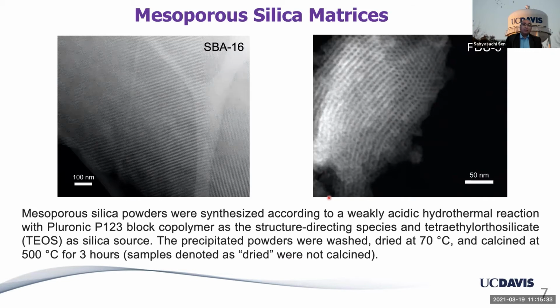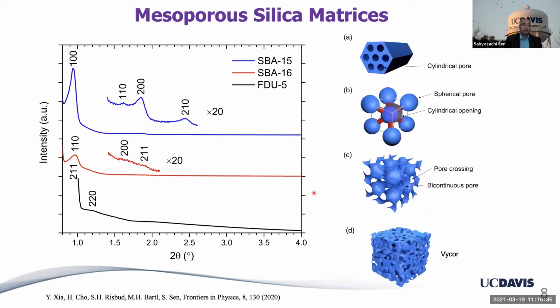So these are a couple of examples of such materials that we have used. Here are some X-ray diffraction patterns from these mesoporous lattices. They agree very well with the literature values. So these are not novel materials, but they're very well characterized materials that have been reported in the literature in the past. And so I'll be talking about, for example, SBA15, which has this hexagonal lattice of cylindrical nanochannels of about 4 or 5 nanometer in diameter.